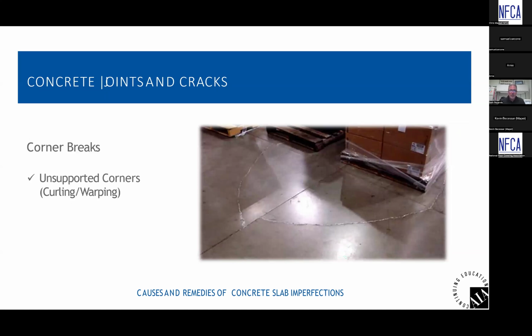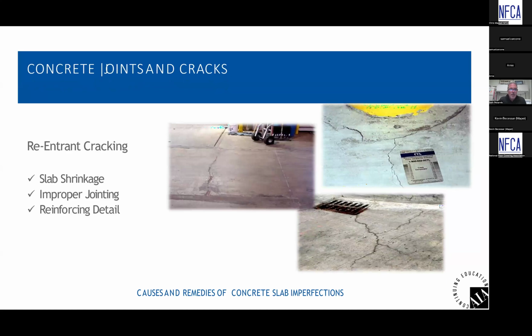Corner breaks, as you see in the picture here, warehouse application, 4 concrete panels coming together. Curling obviously happened here, and then the concrete slab is not supported underneath there, and we had some sort of heavy point load or rolling load here that caused the break to happen because of the curl or the warping that was experienced here. And then you see the corners break, and the concrete falls back down and is in contact at that point with the sub base. Again, if there's curl that's going on, we raise the red flag. Nobody raised the red flag with the curl. A point load or a rolling load caused breakage, as you see here.